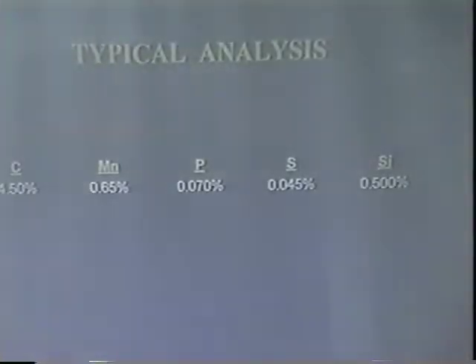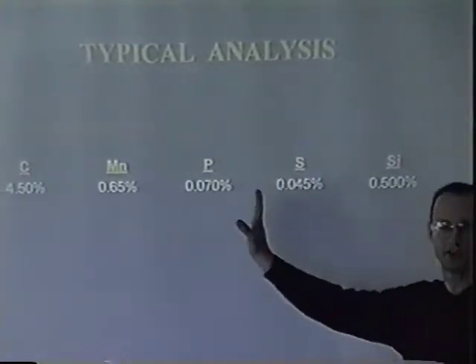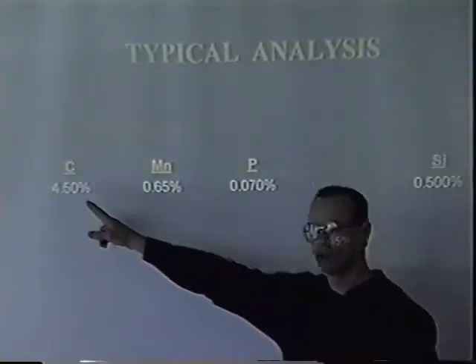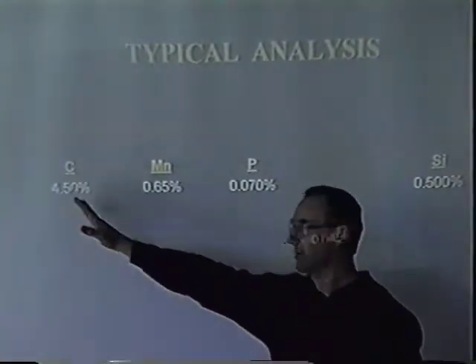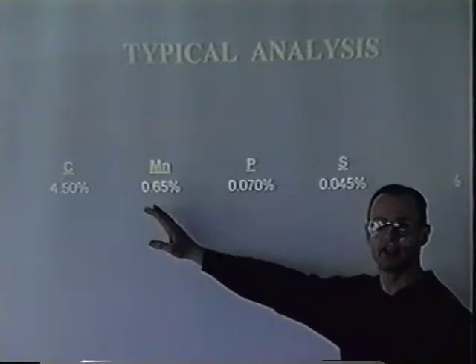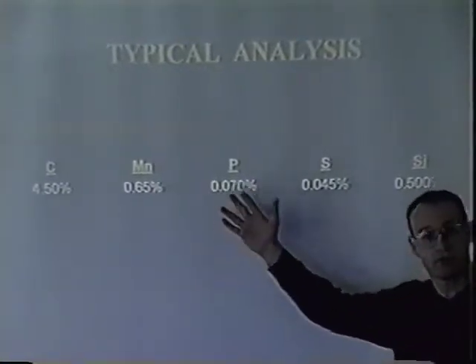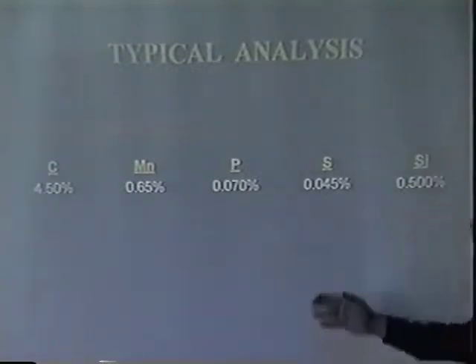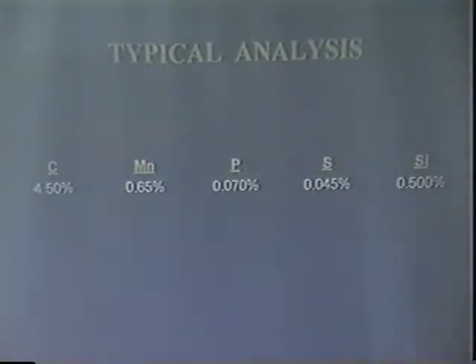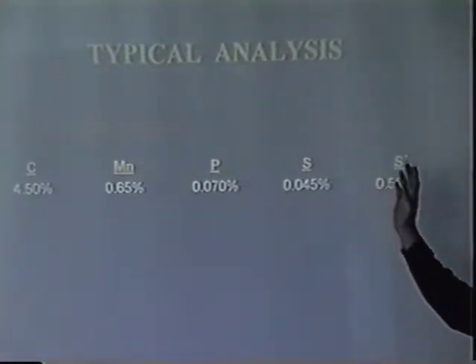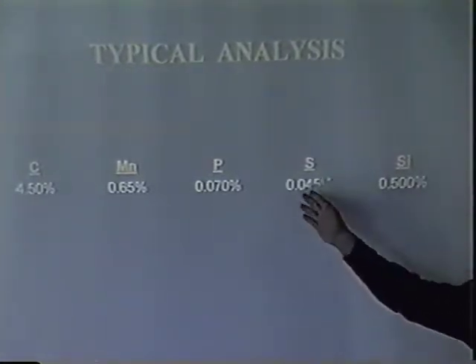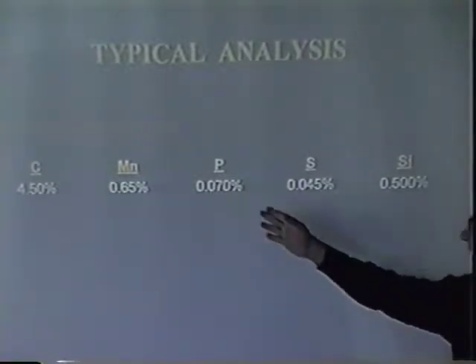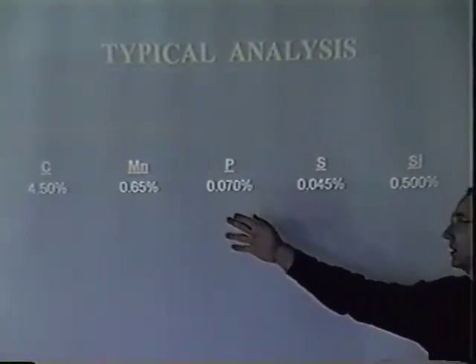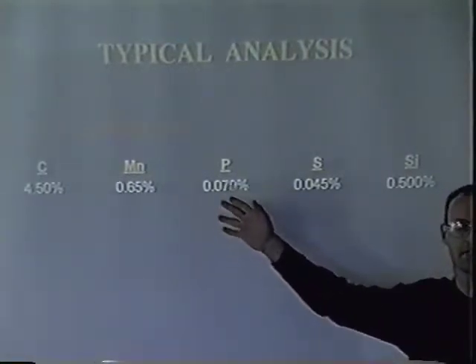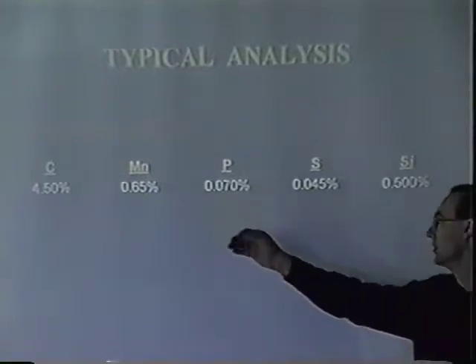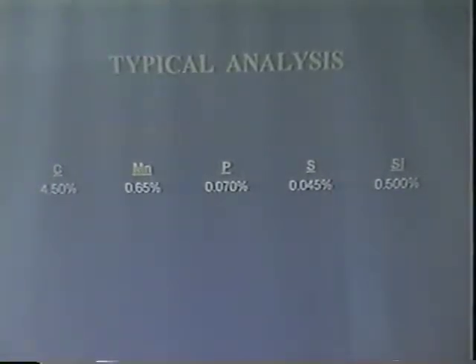And this is the chemistry right here that we would like to see from the blast furnace. As I said, they put some carbon back into the hot metal, about 4.5%. There's some residual manganese left in it. There's phos in it, way more phos than we steelmakers would like to see. Sulfur and silicon. Steelmakers like silicon because silicon generates heat. Sulfur is a problem in the finished product, and phos is a problem in the finished product. Phos will generally give us a little more strength in the finished product than what we want, and it's very unpredictable. Sulfur causes many, many surface problems.